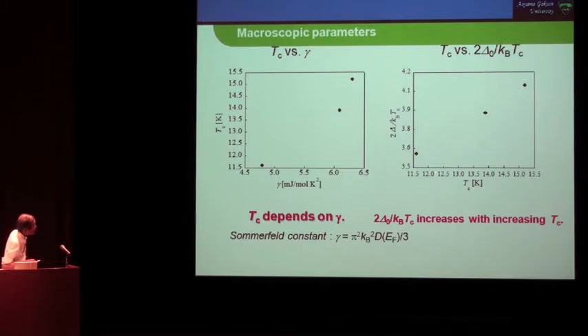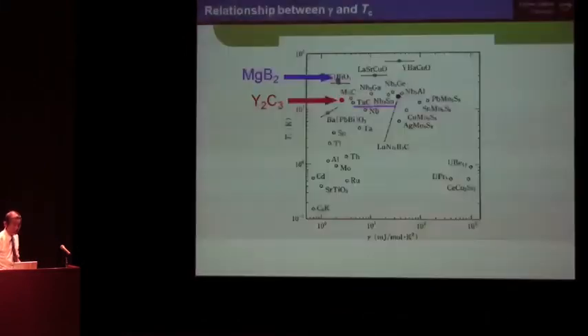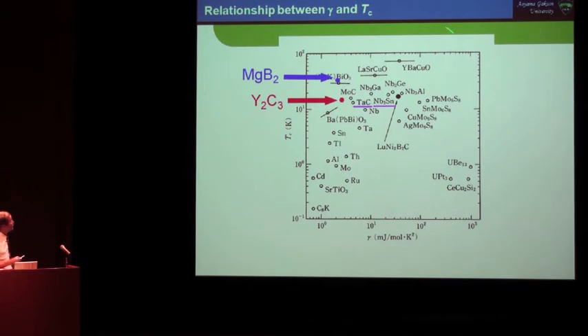However, 2 delta over kB TC is increasing with increasing TC. The relationship between gamma and TC, and also magnesium diboride and Y2C3, are located here in this region.